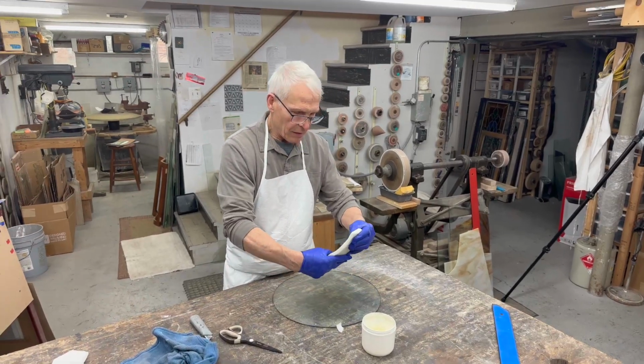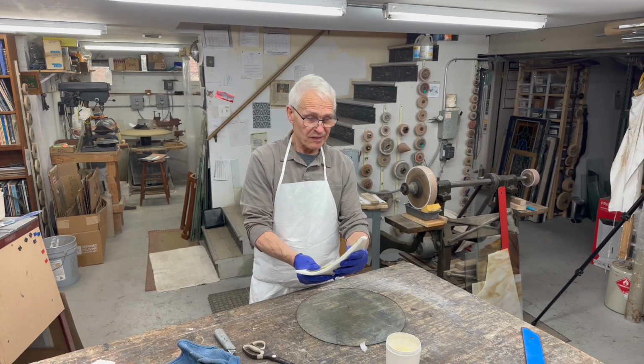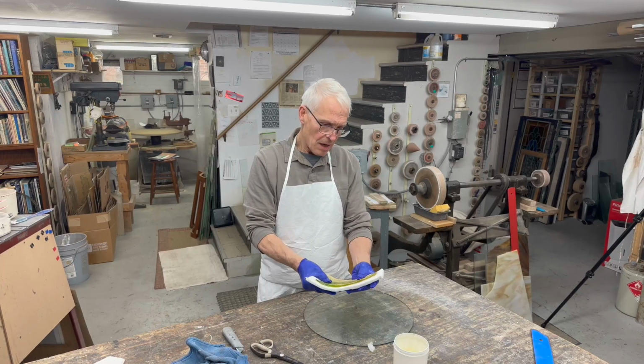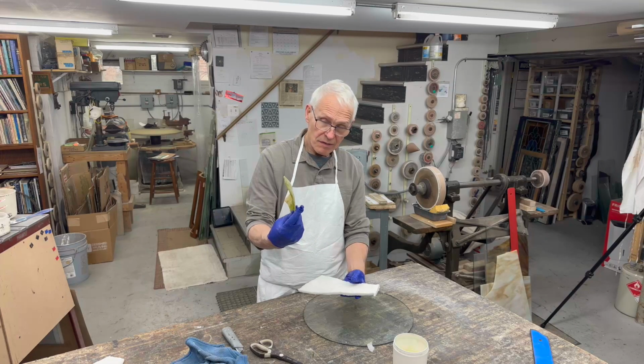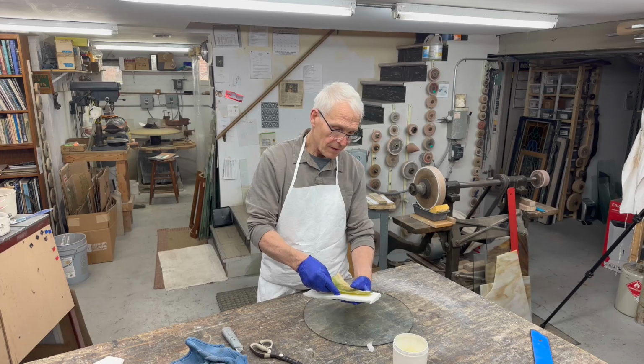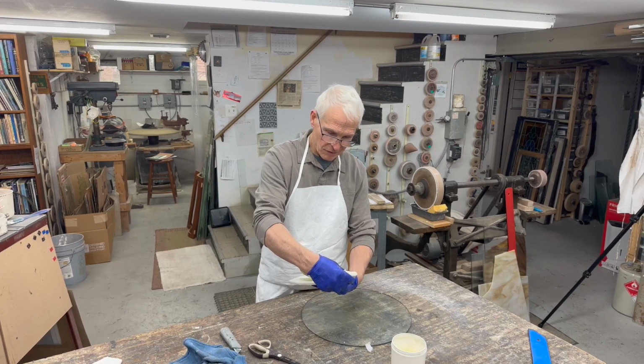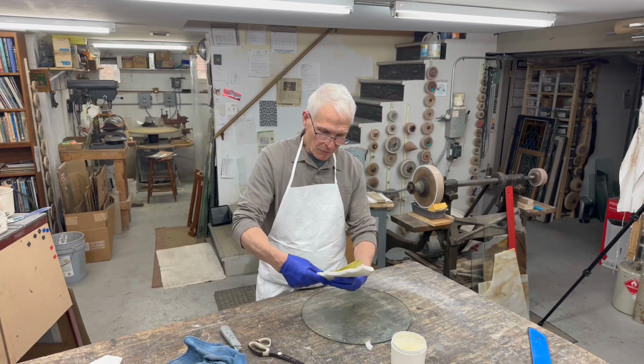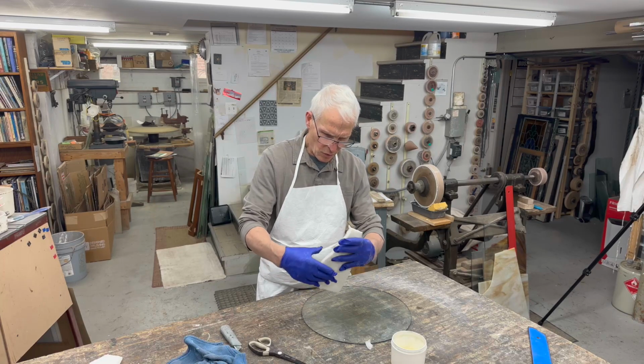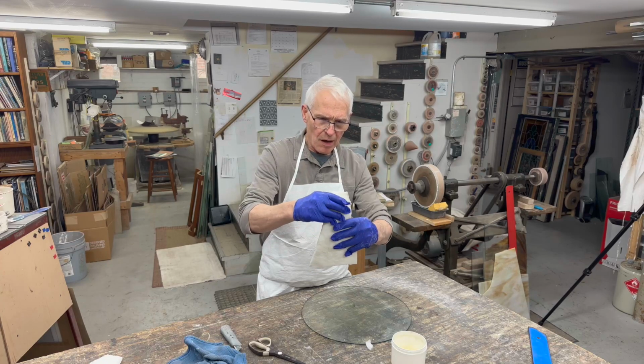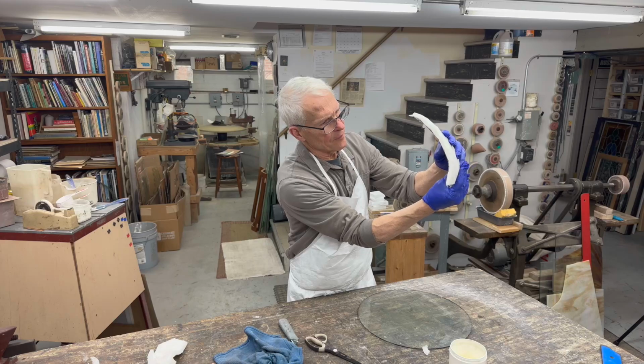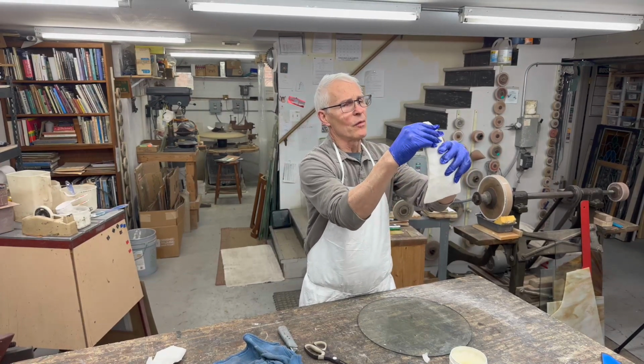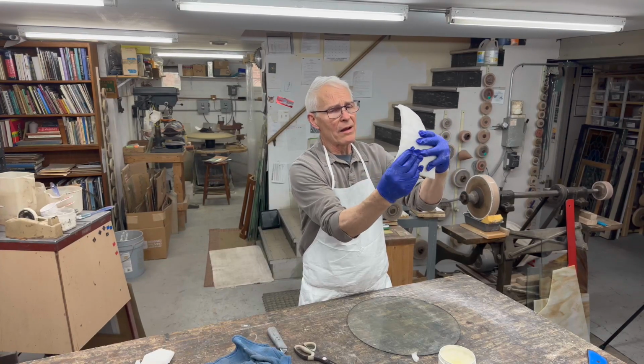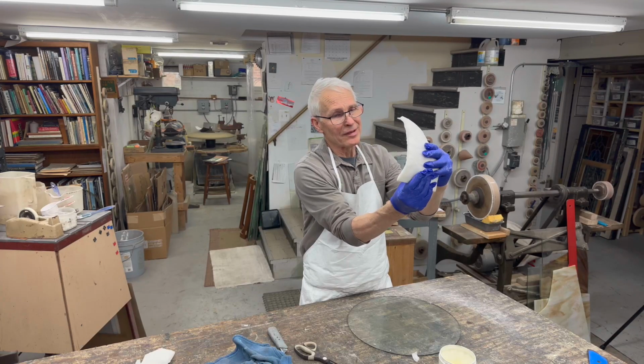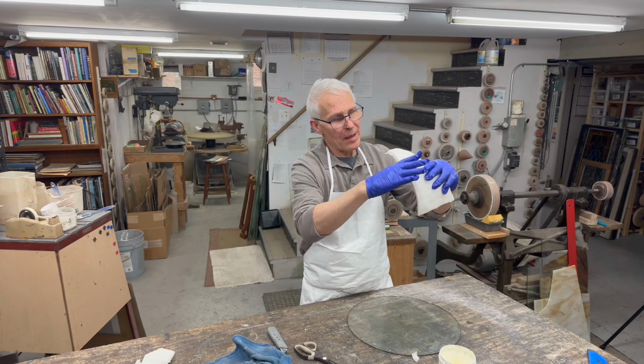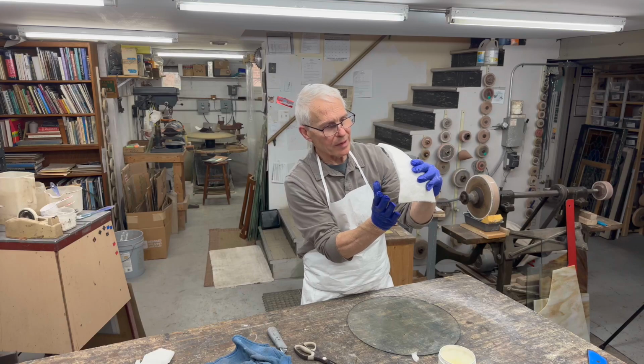Just so you know, I always slump down into the mold. Rarely, if ever, do I slump over the mold. I slump in. The face of the glass, since it's on the mold, you'd think it was going to get distorted, but actually it looks just fine. Slumping over, you need a lot more heat and you have more problems. So you can just take it and work it. If you have a panel or project with a really radical bend, you'll have to work on maybe using some wire to pull it in tighter.